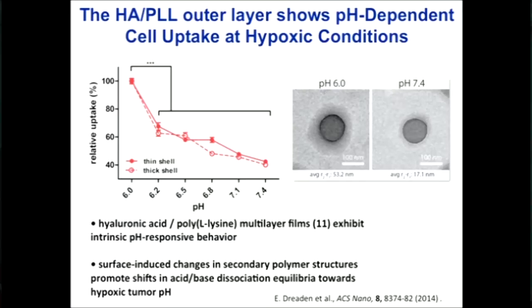So in this case, it turns out that the hyaluronic acid layered with poly-L-lysine, which is a synthetic polypeptide that's positively charged, actually gives us an interesting effect. At bloodstream pH 7.4, it's net negatively charged, about minus 30 millivolts. And it has this thin layer. Can you guys see that? This is a thin little shadow layer on the outer region. When you take it down to just pH 6, which is a more acidic environment, you see that it swells. It also loses its negative charge.